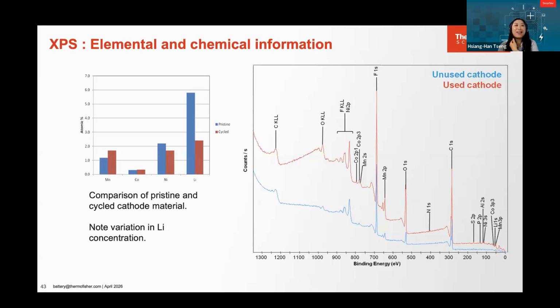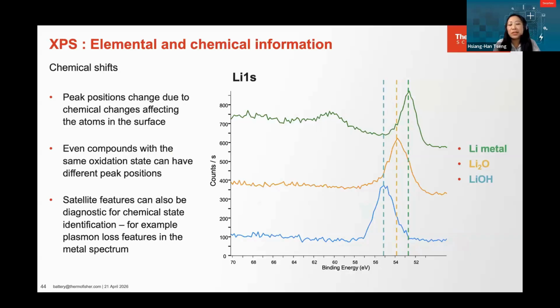Next slide, please. One thing very interesting and useful in XPS is the shifts in the XPS peaks. You can expect these kinds of shifts in the lithium 1s spectrum as well, and that depends on the actual chemistry. I'm showing you samples of metallic lithium, lithium oxide, as well as hydroxide, and you can notice that these shifts appear in the binding energy. That's exactly why it's possible to quantify which elements you have, but also to see the actual chemistry, in this case the chemical states.